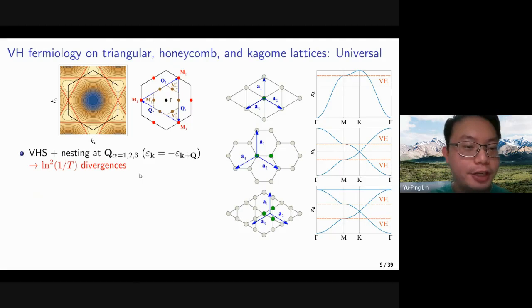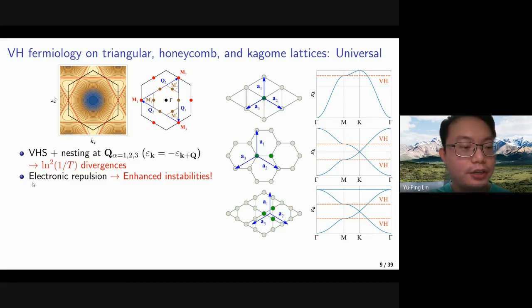If we introduce the interaction, the singularity at the Fermiology will amplify the interaction effect. So what are the singularities at the Van Hove Fermiology? First, we have the Van Hove singularity of the density of states. Secondly, we have the nesting, which occurs at Q1, Q2, Q3. That is, if we look at a point near the Fermi surface and shift it by a finite momentum q, we'll find that they are opposite to each other, and this occurs along the Fermi surface. Combining these two singularities, we will have log-squared divergences, which scale with the temperature. And if we introduce the electronic repulsion, it will enhance the instabilities.